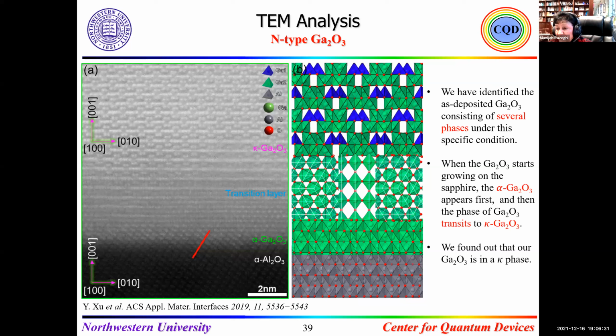Why are you asking about local annealing? To be sure if we can have, for example, the phase transition between kappa and beta happening in parallel at the same time. Yes. My idea was, because you said if you have alpha or kappa or beta grown under different conditions, their temperature stability differs, so I was thinking maybe if the top layer is more resistant or less resistant, maybe it would be possible to...